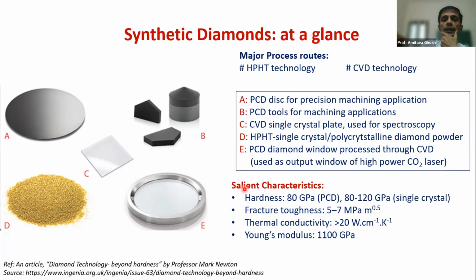If you look into some of the salient characteristics, you can see the hardness of synthetic diamond. It might be a little lower than the hardest natural diamonds, in the order of 80 GPa for PCDs, and 80 to 120 GPa for single crystals. Fracture toughness is pretty high. That is one of the reasons synthetic diamonds are so much preferred. Being a machining specialist, I look at this factor much more critically, because we are going to use these diamonds as cutting tools, maybe in high-speed machining applications, including grinding. Of course, it has high thermal conductivity, which is also required when I use the diamond as a cutting tool. Young's modulus is also pretty high, around 1100 GPa. So this is a very quick glance at synthetic diamonds, in whatever form they exist, and how they are exploited for engineering purposes.